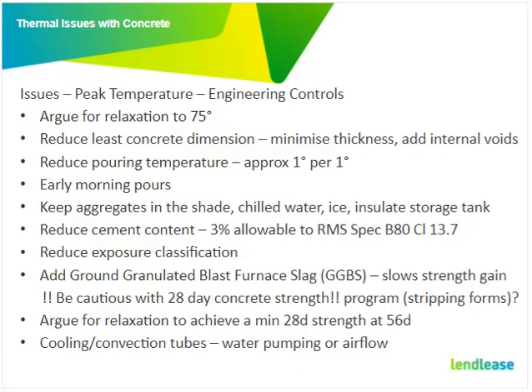I think one of the issues that we have in our job in Queensland is we're having to pump concrete by 1 or 2 kilometres or something, and by the time it goes through and picks up all the friction, it increases its temperature by about 5 degrees. So whatever you pour it into the pump at, at the other end it's another 5 degrees hotter, and then again you can't meet these peak temperature requirements. So it's quite difficult.